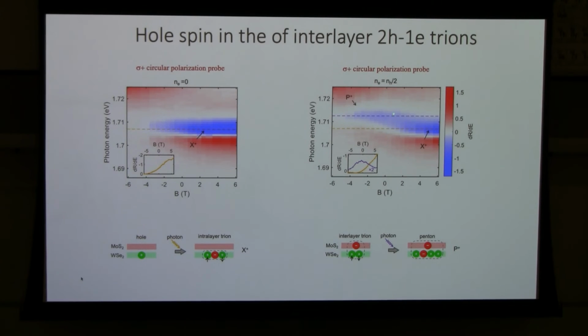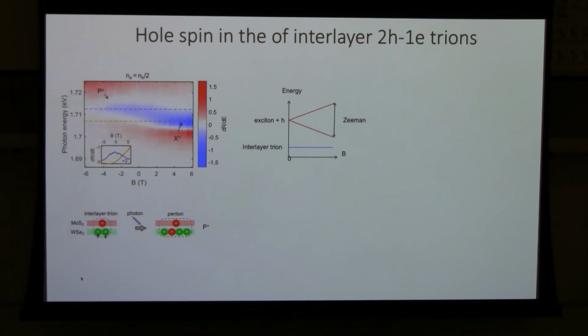But you might ask, what happens at large magnetic field? Why does it disappear, and then we start to see this trion signal very strongly? That can be understood by thinking about the energy difference between the bound trion state versus the exciton and free carrier state, and how they change when you apply a magnetic field. The trion binding energy, relative to the free hole and the exciton, is not that large. When you apply a magnetic field, because the trion hole spin is singlet, the energy doesn't change. But one component of the exciton plus free hole energy keeps decreasing with larger magnetic field.